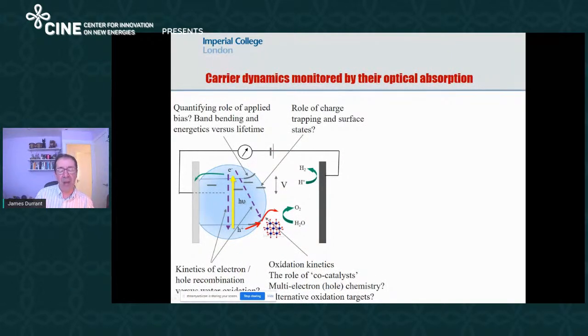If we look in a little more detail at what's going on, then of course, when we absorb a photon by a metal oxide, you generate electrons and holes. What you want is the hole to go to the surface and to drive the chemistry. But in practice, what happens is the hole recombines with electrons, either in the bulk or on the surface. We also have to worry that many of the materials we talk about are defective with lots of traps, and this can indeed also mediate recombination. And so it's trying to understand these kinetic challenges that I'll be talking about today.